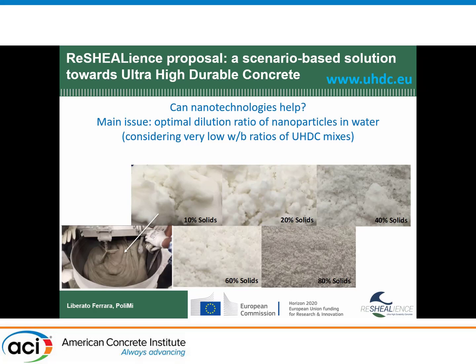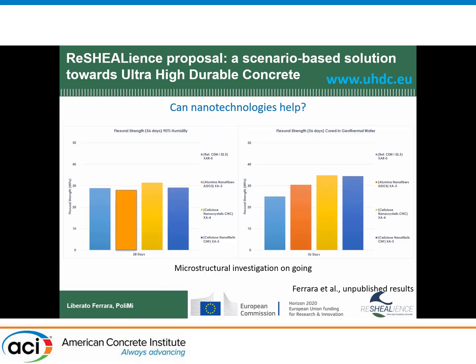The interesting thing is that we obviously tested the material in standard 90% relative humidity curing, and we observed that there was no significant difference between the reference mix and the one with the nano additions. But the other thing was that we cannot tell the company that they have to wait for 28, 56 days before just putting the water into their basin, because they want it immediately operating.